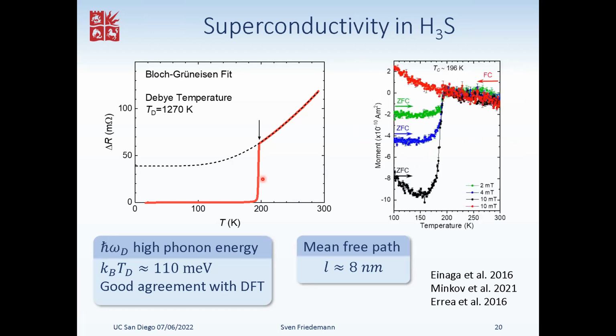Diamagnetic measurements are extremely hard to get absolute values from. First of all, the background subtraction is tricky with the pressure cells. The next challenge is if you were to convert that into a magnetization rather than just a magnetic moment, you need a good understanding of the demagnetization behavior of the sample. That's very tricky to get, because for that you would need to know the geometry quite accurately. Hence, this is not an absolute measurement. It's a drop in the magnetic response, but not an absolute measurement which shows you a susceptibility of -1.